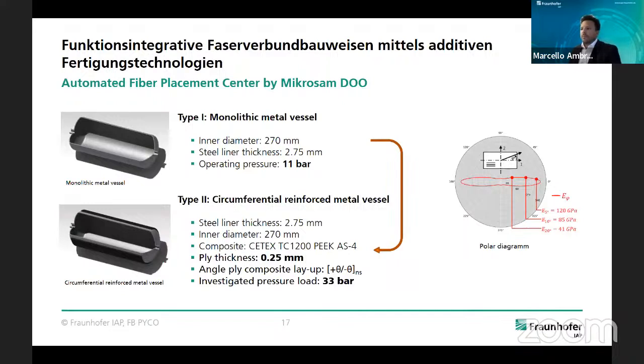Here's another example of how we updated a type 1 pressure vessel, a monolithic metal vessel, to a type 2, a circumferential reinforced metal vessel. The operating pressure of the type 1 pressure vessel is around 11 bar, and just by adding a 0.25 millimeter ply thickness, so fiber reinforced plastics around the pressure vessel, we triple the operating pressure. The ply thickness of 0.25 millimeters on 1 meter is maybe not even 1 kilogram of material that we add onto the pressure vessel, but we gain triple the operating pressure, and this is quite impressive. This is also, as I said in the beginning, why it is so important to keep the right orientation of the fibers.